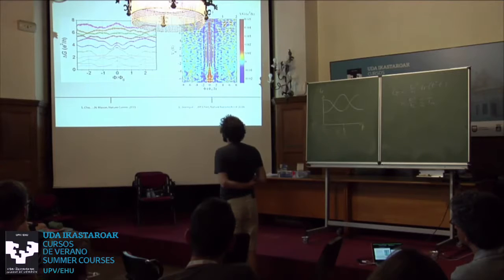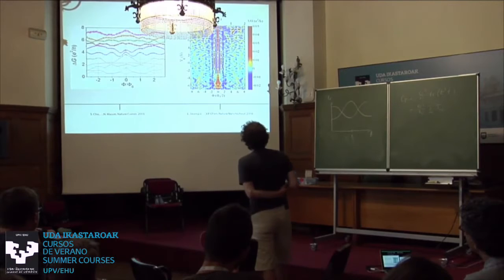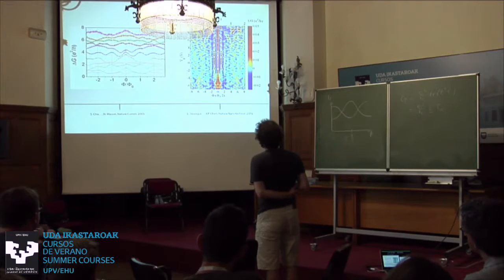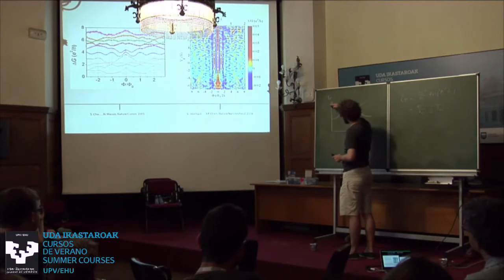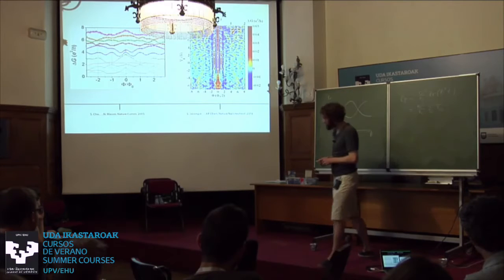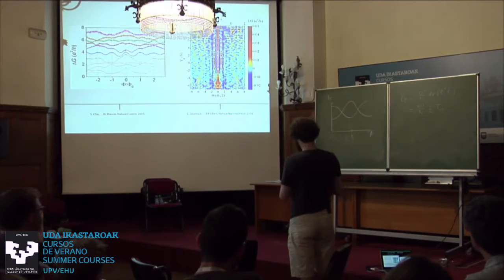Now this one is pretty interesting because what they do is they can vary the chemical potential, and if you vary the chemical potential, you should see oscillation that goes from having a maximum at 0 to having a minimum at 0. And if you look at this with a loving eye, you can see precisely that happening.